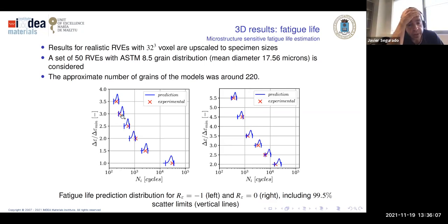What is interesting in this prediction, I'm going to emphasize, is that it's absolutely multi-axial and general. It means I fit the crystal plasticity law with a single experiment, and I take maybe 2 fatigue experiments to fix some of the points. But now, if I take my RV and, instead of applying a uniaxial cyclic history, I have a multi-axial cyclic history or a different type of cycles, then I can still do the same. So I can get the fatigue indicator parameter distribution, I can make the statistical study, and I can provide life.